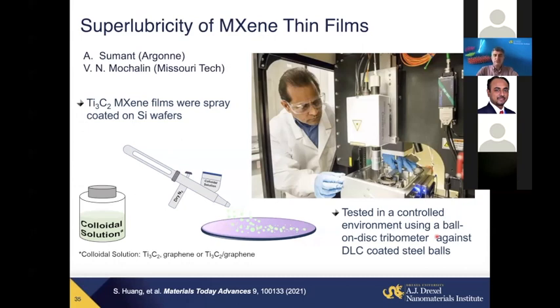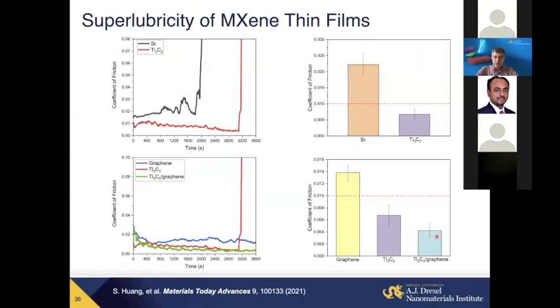Diamond-like carbon is known for its very, very low friction coefficient, also eventually showing superlubricity. It means an extremely small friction coefficient. And what they found is that actually Ti3C2 shows under these conditions a friction coefficient that goes another order of magnitude below what I showed to you in the previous study, to 0.01, which means basically superlubricity here.